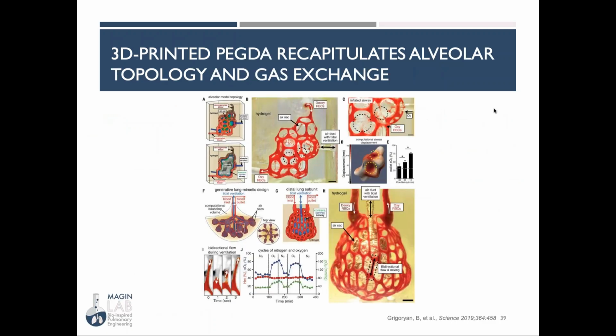One of the most exciting things that's come out of using fully synthetic materials to model the lung came out of Jordan Miller's lab. So they have been able to 3D print this incredible system that mimics an alveolus and the capillary network around it. And so you can see here, there's an alveolar structure. It can be filled with air. The capillaries around it can be filled with blood, and they can actually do gas exchange and oxygenate the blood inside this 3D printed model. So this was incredibly exciting. And when I was talking to my MD colleagues in the pulmonary division, it blew their minds. They had no idea that we could engineer something this complex.